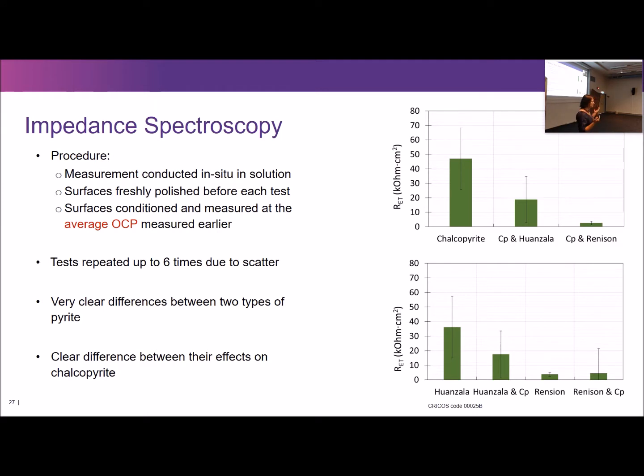The tests were repeated 6 times because I had a lot of variability, with some very, very clear differences between the two pyrites. So here, the higher the resistance to electron transfer, the less your mineral is likely to react. So Chalcopyrite has a relatively high resistance compared to the rest of the minerals, so it doesn't want to react. And then you've got the Chalcopyrite when mixed with a Pyrite, the resistance drops, so it becomes a lot more likely to react with something. And then when present with Renison Pyrite, it drops even further and it becomes a lot more likely to interact with something, either solution or another mineral.